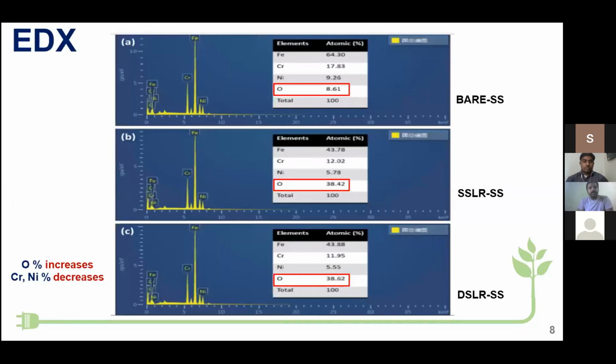Next is the EDS analysis. The as-fabricated laser textured material has been subjected to EDS analysis. From this graph, we can identify that the concentration or percentage of oxygen is increasing, which is highlighted in the red box. We can see from figure A that the bare stainless steel has only 8% oxygen, whereas single side and double side have nearly the same, about 38%.